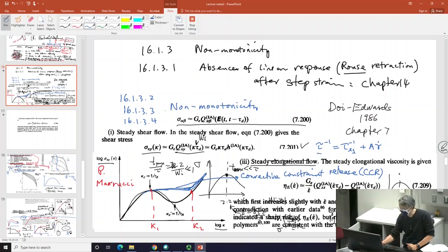Remember, I'm drawing in the rate mode, the reciprocal of it. So they are claiming that in the tube model the chain can escape from the tube confinement because the shear is carrying them out. So in that limit, you don't have this over-orientation because they already got out. So this rescued them so that there will be no shear banding.